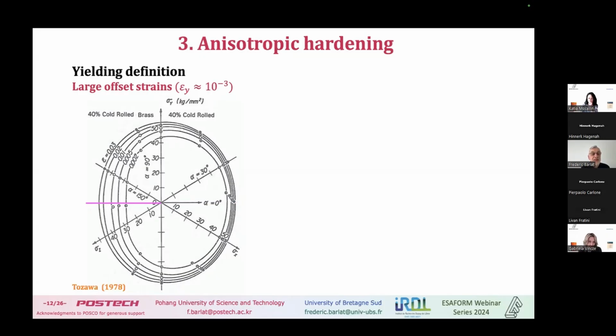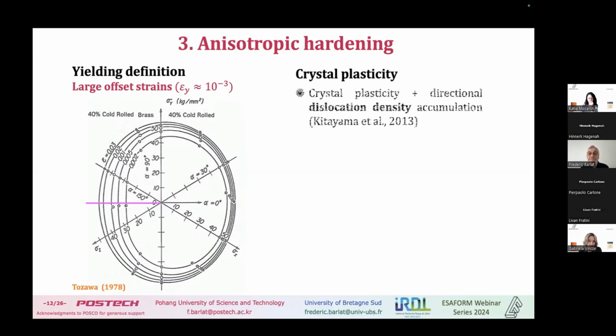And I would say here I see more distortion than a translation, and there can be some translation of the yield surface, but yeah, it's difficult to say. So crystal plasticity, if we do crystal plasticity together with directional dislocation density accumulation, so the regular crystal plasticity model is not going to show you what I'm going to show you. You have to have the interaction between dislocations to capture this, but what you get is something like this.